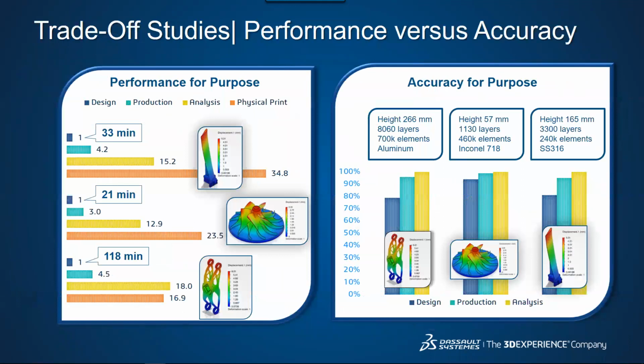Okay, so the real value in process simulations for additive really comes from, can we arrive at a successful build configuration without doing physical trial and error? But for this to actually be possible with simulation, our simulation runtimes really have to be significantly faster than our build times, without a significant loss in accuracy of the results. Again, I mentioned our simulation framework allows the solution fidelity to be controlled through mesh size and time incrementation. So this means that we can do trade-off studies to quantify solution accuracy versus performance, and this is what this slide here shows. We've characterized the levels of solution fidelity as design through production to analysis, where design is a fast solution, which is just required in aiding design decisions, whereas analysis is a refined type of simulation where we have one build layer per time increment.